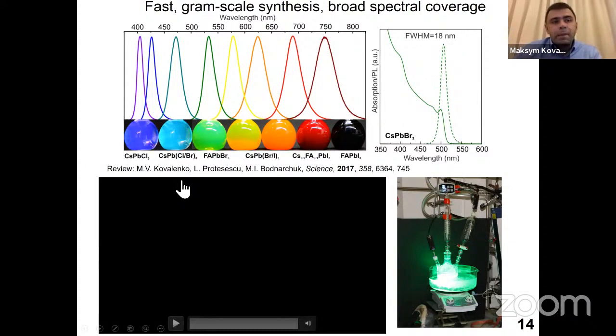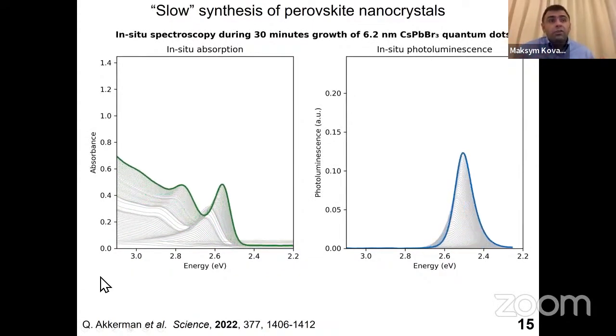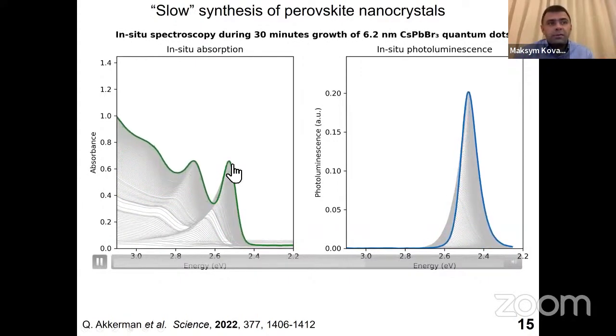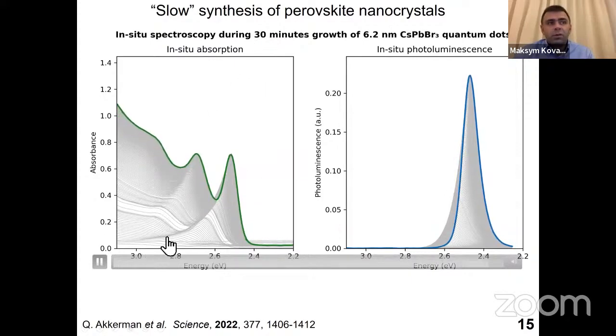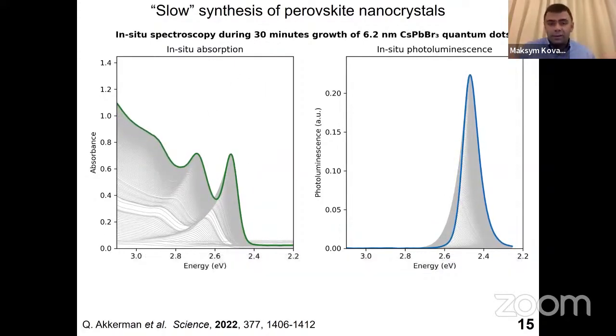For about 6 years from this initial, first edition of the synthesis, we used only this type of chemistry, which was very fast because the ions co-precipitate very rapidly. But then 2 years ago, we began to explore a new synthesis pathway, and I show you the outcome of that new synthesis, which was just published last month. Here you see that you can actually have this whole synthesis much slower. So you see the absorption spectra of these quantum dots measured within 30 minutes. So this whole progression is half an hour instead of 1 second or less. So now you have a synthesis which is much slower, much easier to control, and everything occurs at room temperature. So you don't even need to heat it up.